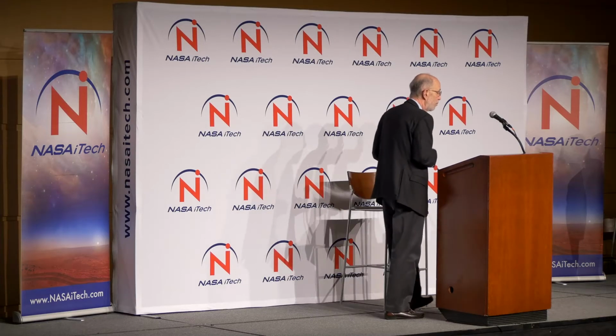Yes, I have a question over here. Alan Ayers. I was questioning whether these electrolyte and salt combinations are compatible with all the different types of electrodes or cathodes in the lithium-ion, like manganese dioxide and cobalt-based. Absolutely. We've tested it against a suite of potential electrodes, both anodes and cathodes. And what we found is whether you have a cobalt oxide or an NMC or some of the other higher energy electrodes that currently are not available to the market because of the failings of the organic electrolyte that we are going to replace, we haven't seen any problems as far as compatibility with the various anode and cathode designs.